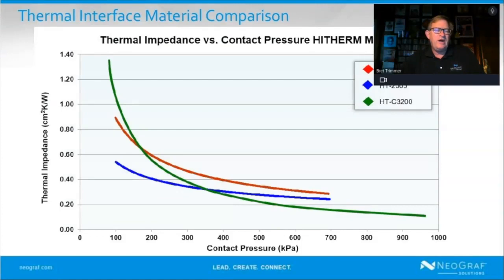A question that we get all the time is on thermal conductivity of the material. When you're talking greases or thermal pads, they often advertise the performance in terms of thermal conductivity. For a solid material, thermal conductivity is a relatively meaningless number. If that weren't the case, a sheet of copper has a Z direction thermal conductivity of 400 watts per meter Kelvin. You would think it would make an outstanding thermal interface. But the reason no one uses copper for thermal interface is that the impedance is very, very high. So you always need to take a look at the thermal impedance versus the contact pressure you put on the material. And then you can decide if it's going to thermally meet your needs. So it's a much more accurate description of the material rather than just straight thermal conductivity.